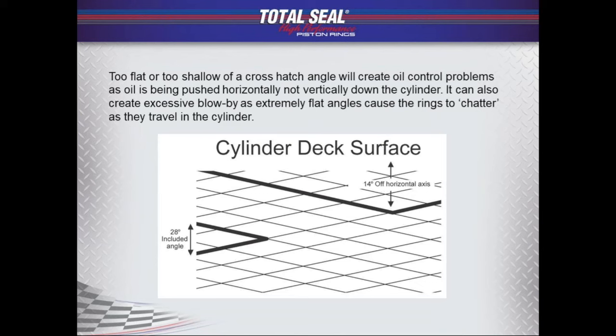But the same can be said for oil. There are engines out there that have very long cylinders, very tall compared to the stroke. A more vertical crosshatch angle helps to get oil propagation up to the top of the cylinder. A perfect example is a Harley Davidson. A lot of Harleys from the factory run a 60-degree crosshatch angle. The more vertical angle helps promote oil migration up to the top, where they're not getting enough oil simply because of the length of the cylinder.